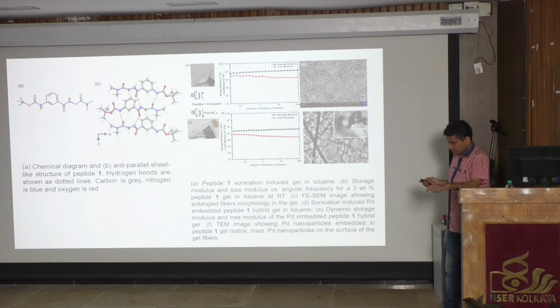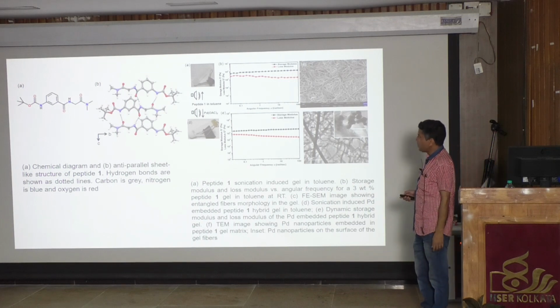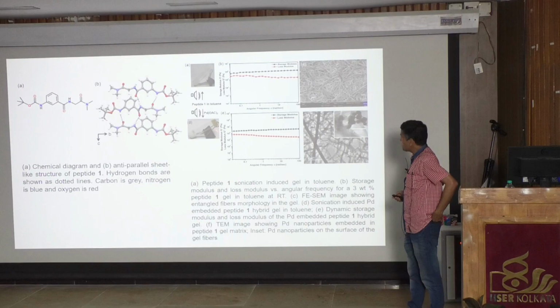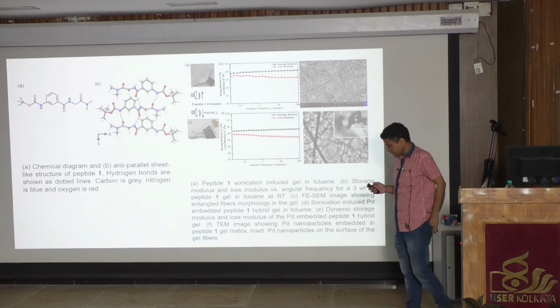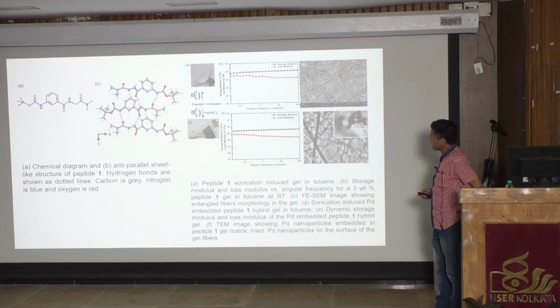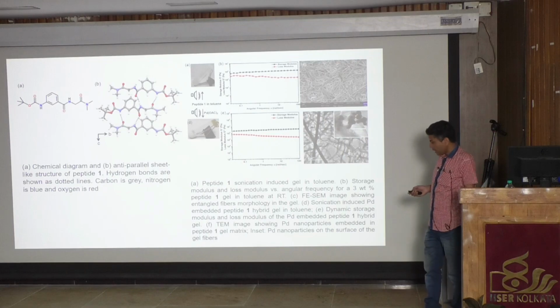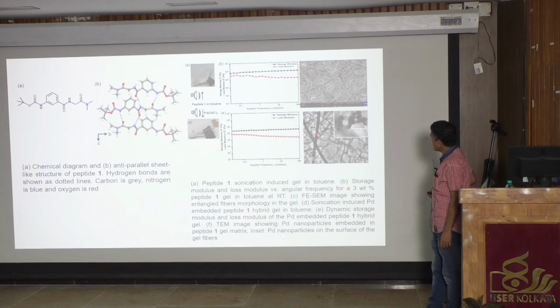From X-ray crystallography, this compound forms an antiparallel beta-sheet-like structure, and finally it forms the fiber and forms a gel in organic solvent. During gel formation in toluene, if we use palladium acetate, the palladium acetate will interact with the amine and dimethylamine and convert to palladium(0), palladium nanocrystals, and those nanocrystals will cover the gel surface. So we have studied, without palladium and with palladium, all the rheology and morphology of the gel.